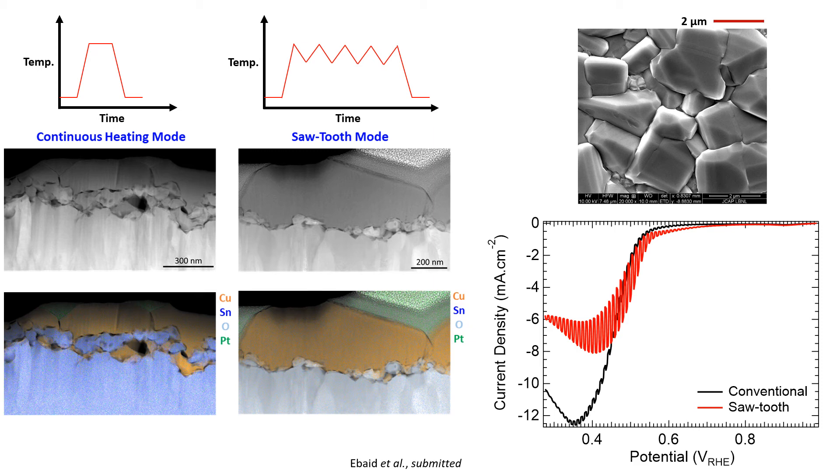What's noteworthy here is that we also cannot drive to very high reduction potentials as the material starts to reduce back to metallic copper. After this dark reduction wave, you can see the significant decrease in photocurrent. We think that's due to the formation of metallic copper inclusions, again that kills the photocurrent.